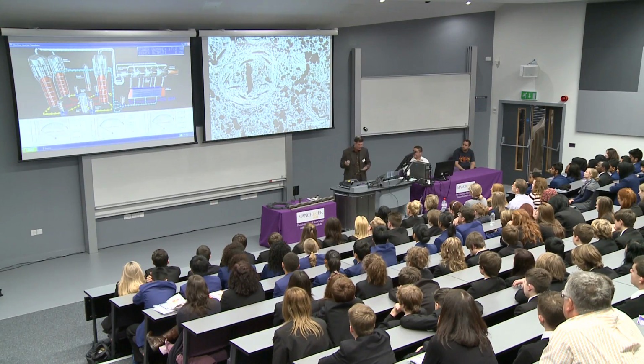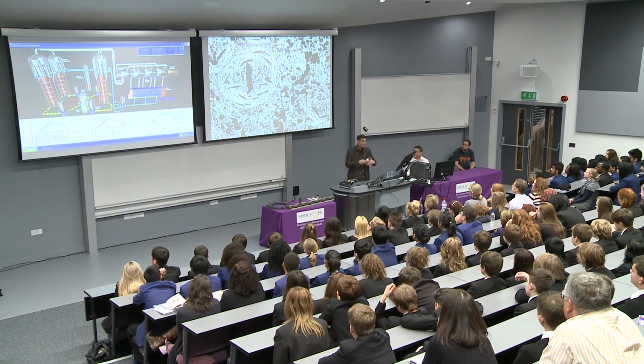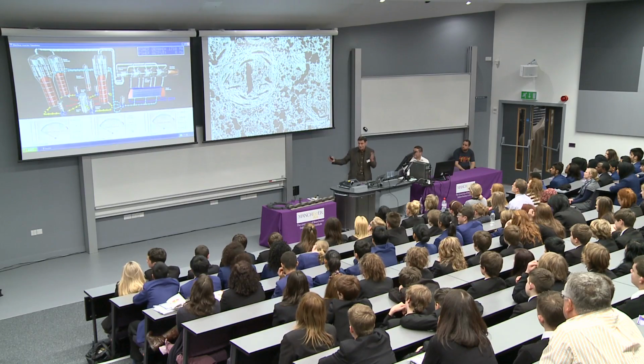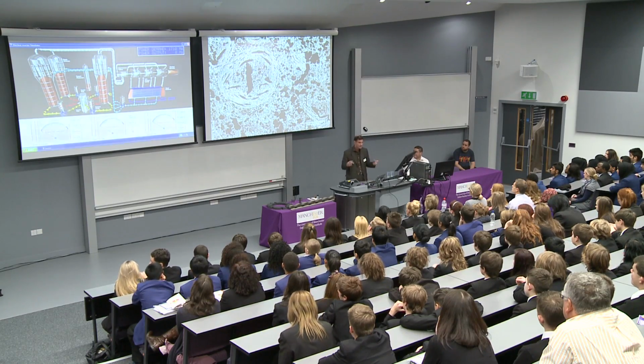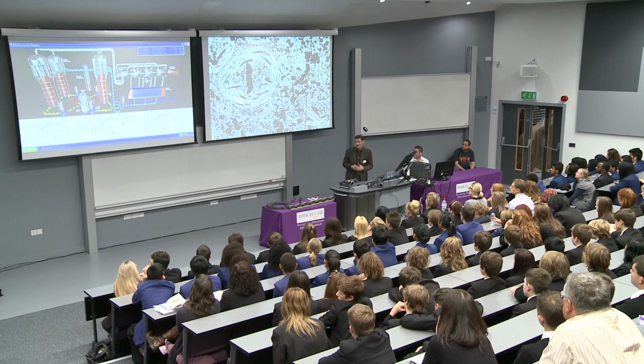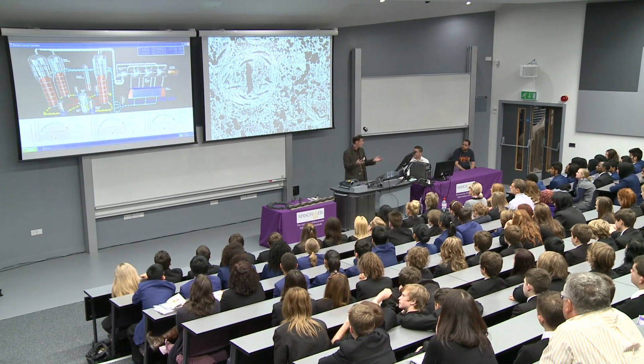But during life, the microstructure changes. In fact, it becomes more porous. The dimensions of the graphite change. It heats up, and the radiation damages the graphite. And actually, that creep process, that slow, steady elongation of that material I showed you earlier, also occurs in the graphite. So you've got all of these processes going on together, and what we need to try and do is understand those and be able to predict them. Well, the key for doing that is to relate the microstructure to the properties.